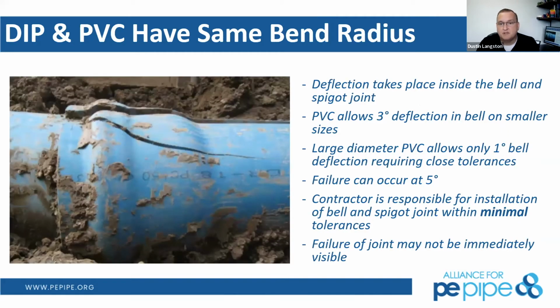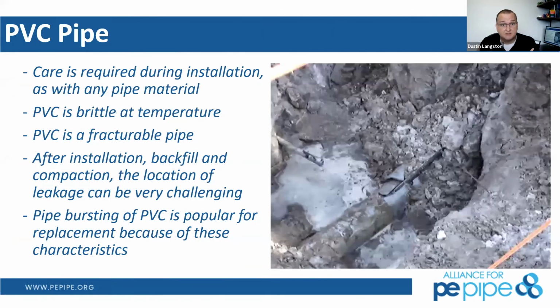So back to that bell and spigot joint, deflection takes place again inside of that bell and spigot joint for PVC and ductile iron. PVC allows 3 degrees of deflection in smaller diameters, only 1 degree of deflection in larger diameter PVC. But failure can occur at as little as 5 degrees. So it's a pretty tight window of what's allowable versus what can cause an actual bell failure in the future. Again, these are installation issues, but this is what the city of Calgary was seeing.